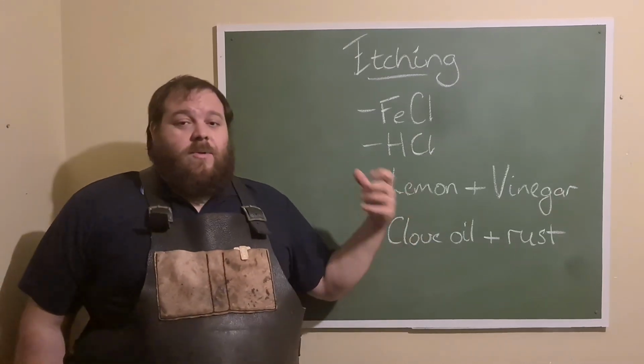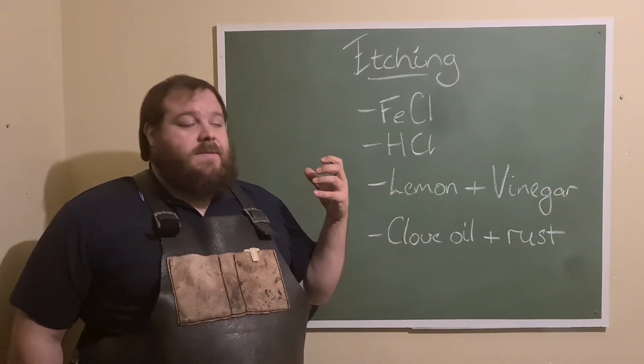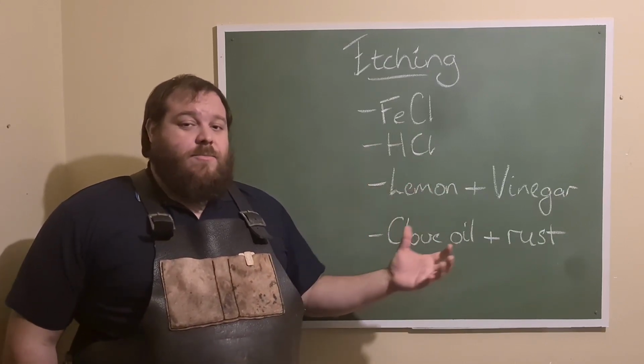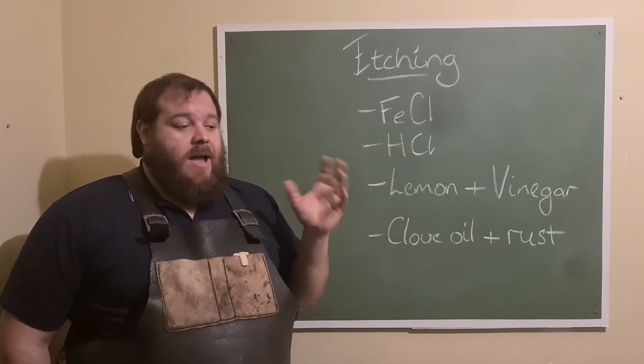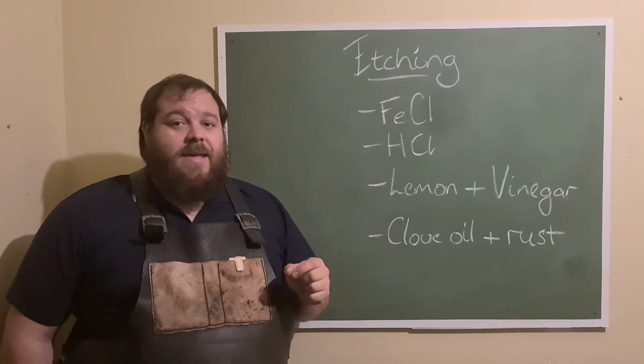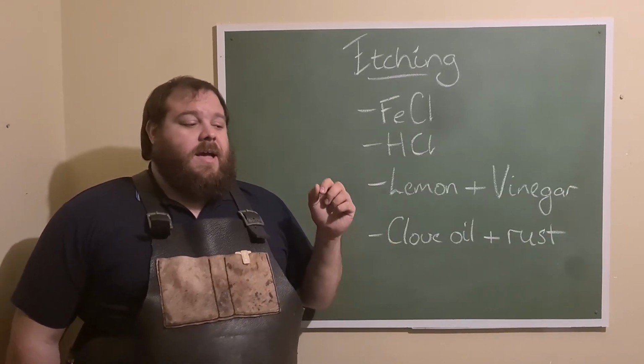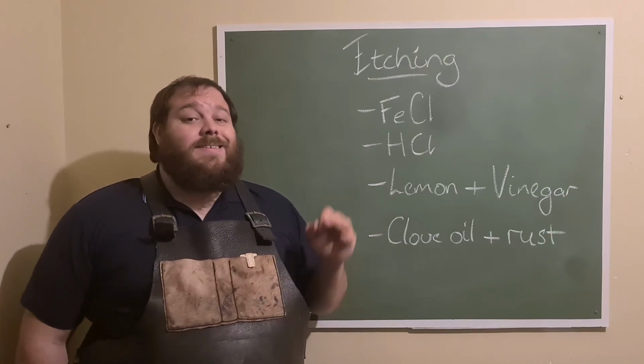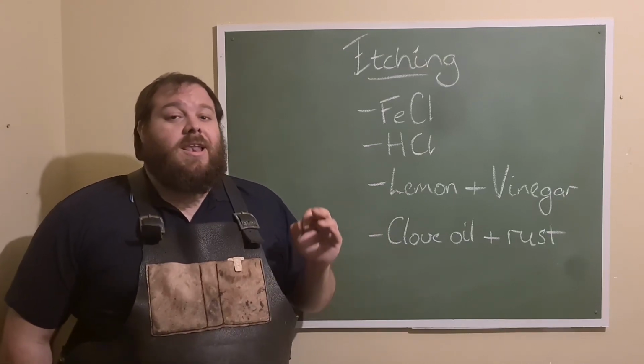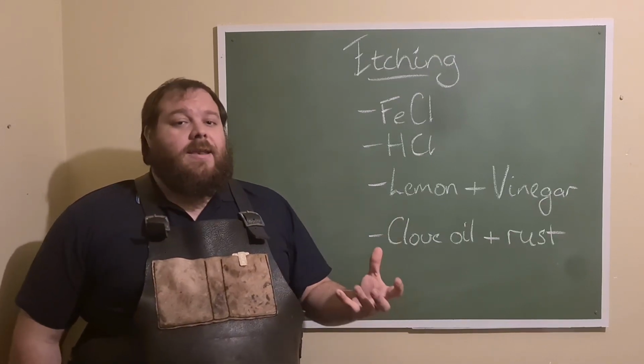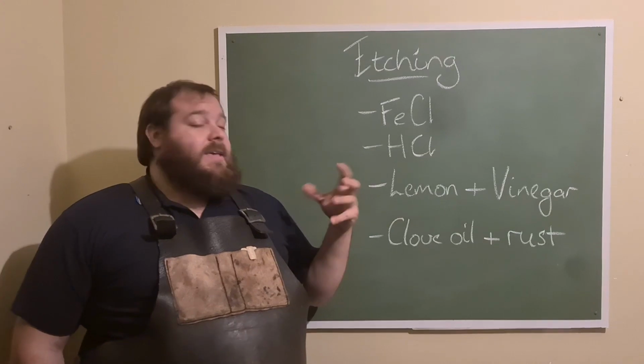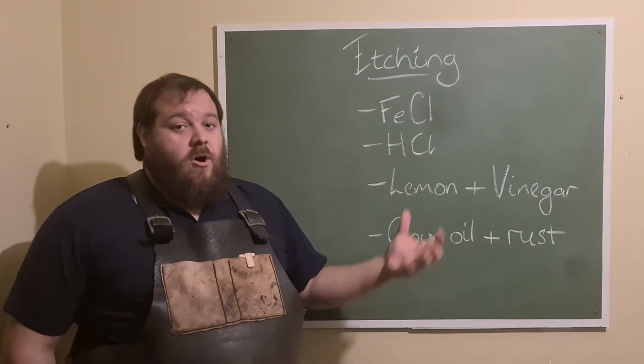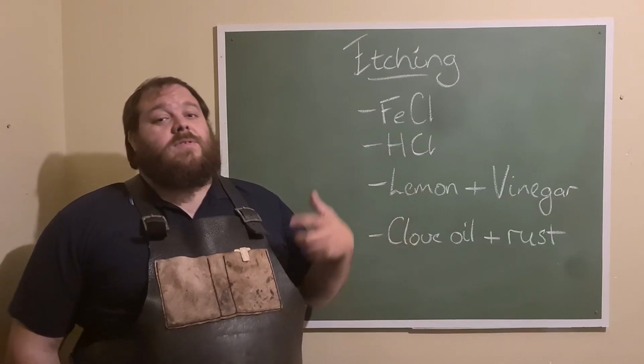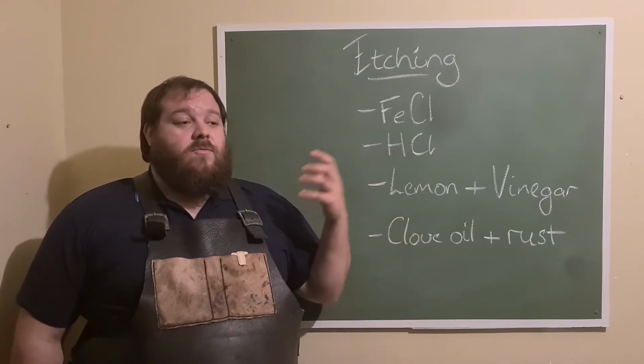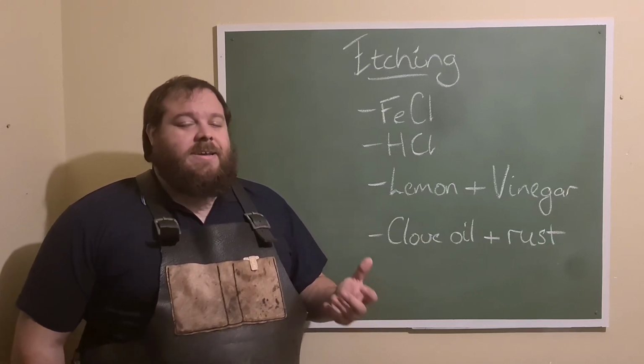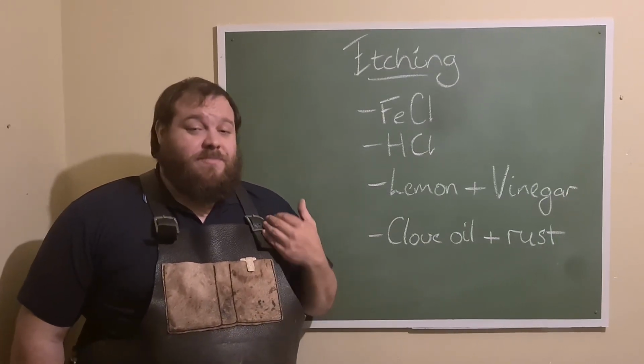My favorite, and the one that I go to normally, is a sequential etch of lemon juice and then vinegar and back and forth. I don't use a mix of the two because the two different acids, both acetic and citric acids, attack the steel in very different ways. The vinegar darkens the steel slightly, and the lemon juice lightens the pearlite, so it really brings out that natural Hamon. But it is a very iterative and long and monotonous process, because you have to do it multiple times over, maybe an hour, 2 hours of reapplying and reapplying, which can be very tedious. So I understand it's not everyone's choice, but it is my favorite.